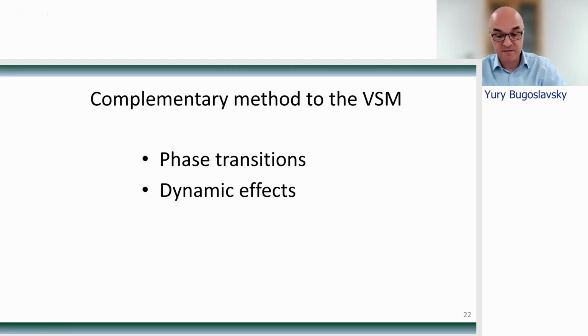ACS presents a very useful complementary method to the VSM. It is particularly useful in studies of phase transitions, not least for the fact that the phase transitions are often marked by sharp peaks in susceptibility. So it's a very strong marker for your phase transition. And it is possible to make easy measurements using different frequencies in a wide range. This method also provides an insight into the dynamic effects in magnetic materials and superconductors as well.